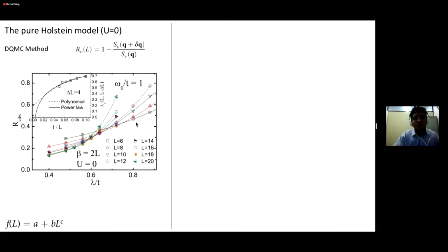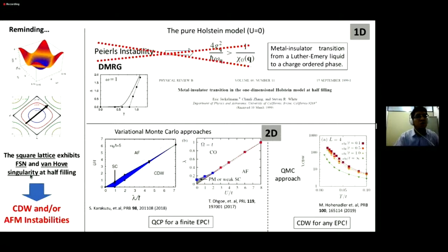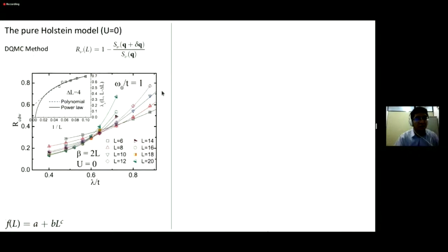But basically, what we saw was that, differently from the 1D case, for the 2D case we have a CDW formation for any electron-phonon coupling. For any electron-phonon coupling, the square lattice leads to CDW formation. And the reason for this different result is that, different from the 1D case, in the square lattice we have this Van Hove singularity. The Van Hove singularity also leads to a divergence in the electronic susceptibility, making your electrons much more susceptible to any perturbation. So this is the reason for the difference between 1D and 2D.